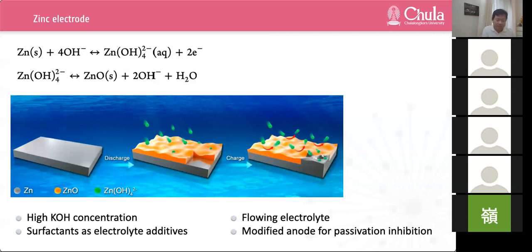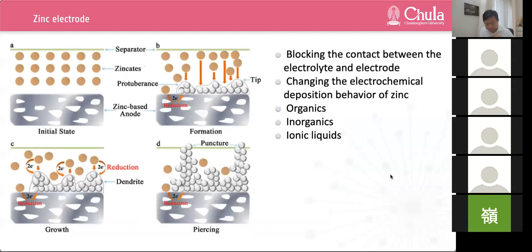The selection of ion-sieving nanoshell components such as the graphene oxide, titanium nitride, titanium oxide coatings, carbon coatings, silica-based coating, and ionomeric hydroxide conducting polymers is required to create desirable environment for the free transportation of electrons and therefore make zinc oxide electrochemically active. And the next problem related to zinc anode is dendrite formation.